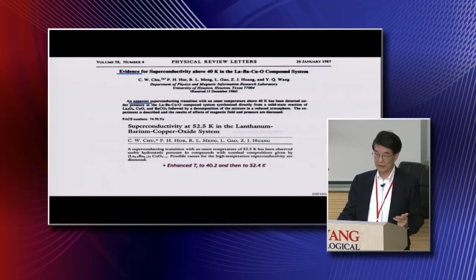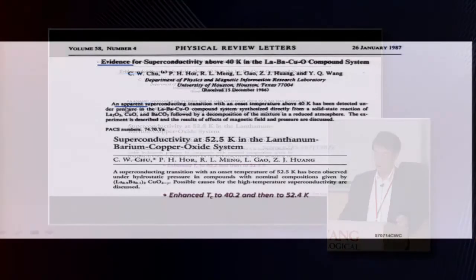The reason for that is that we reproduced the results, we immediately applied pressure to it, and we got the temperature to about 40 degrees. I'll tell you, at that time people were very cautious. For example, the chief editor of PRL, Myron Strongin, actually suggested I change the title. Originally, I said superconductivity about 40 degrees, and he said, why don't you make it softer, instead call it evidence for superconductivity, and so on. And then also my abstract, he proposed to change it. Instead of talking about a superconducting transition, why don't you say an apparent superconducting transition? So you can see at the beginning, people were very cautious.